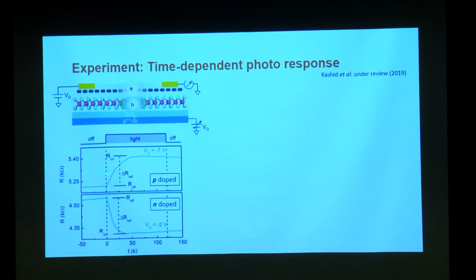So suppose I look at the electrical current in the graphene layer, and I look at how long it takes to build the current after you shine light. That turned out to be in the order of tens and hundreds of seconds. But optically, the exciton breaks in 1 picosecond, and the current transport occurs in 1 nanosecond. Where have 9 orders of magnitude of time gone? This is the question that we couldn't understand for a very long time.